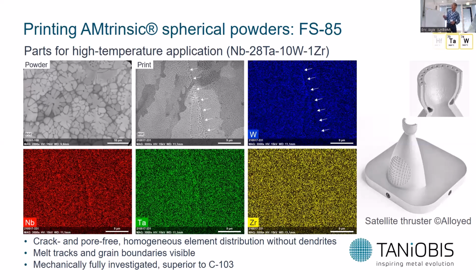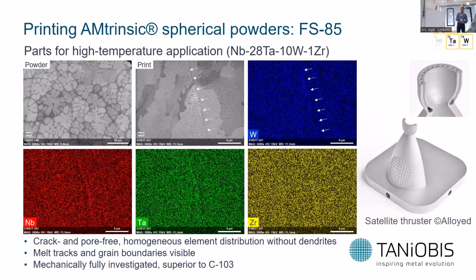What you see, on the other hand, are clearly crystalline domains, and the melt pool boundaries, indicated here by the white arrows. If you go to the elemental maps, so tungsten, niobium, tantalum, and zirconium, you see that in contrast to the precursor powder, the elements are distributed extremely homogeneously throughout the sample, except for the melt pool boundaries, where you can see in all images a very slight inhomogeneous distribution of the elements. But this is associated with different cooling rates of the elements, which is relevant, of course, at the melt pool boundaries. So this is an example of a material which can nicely be printed.